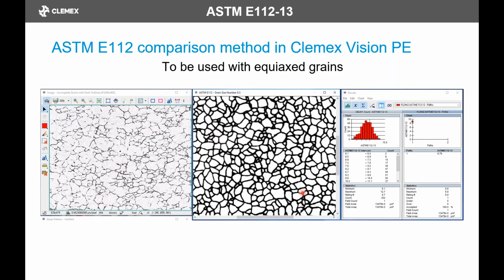So we're getting into the Clemex Vision PE. If we look at the first method that we talked about, we have a grain size number, like in this chart here. We have a grain size that we would look at from a live image, and we would look at the chart here, and we can scroll, and the grain size value will change. It's 8.5, but if you scroll up, it will go 9, 9.5. It normally goes to 10, and if you scroll down, rather, you will have the actual grains that are coarser. We can see here that we have a grain size and an automatic measurement just to compare. We have 8.7, and the chart seems to be pretty good at 8.5. Normally the idea is to have a chart if you don't have a reference to do it automatically.